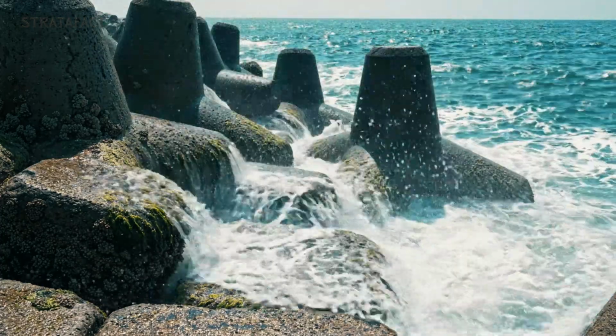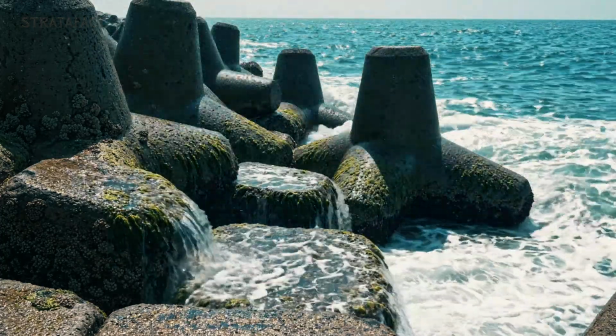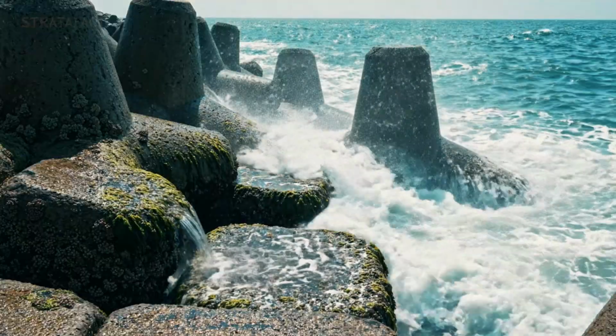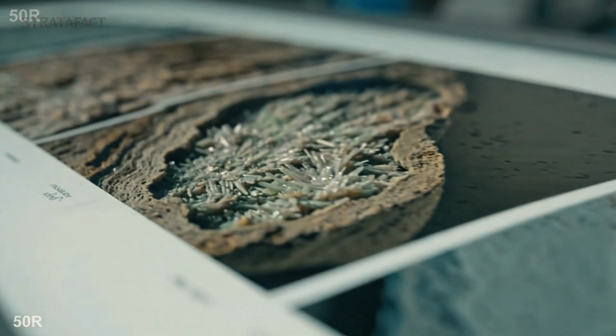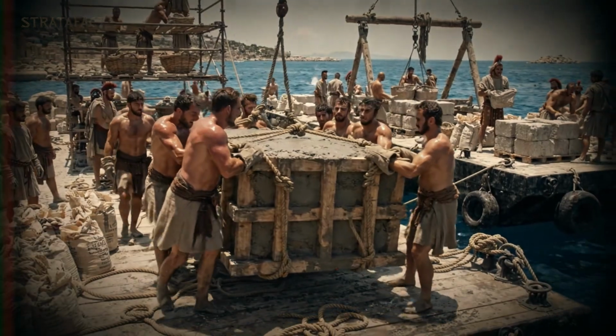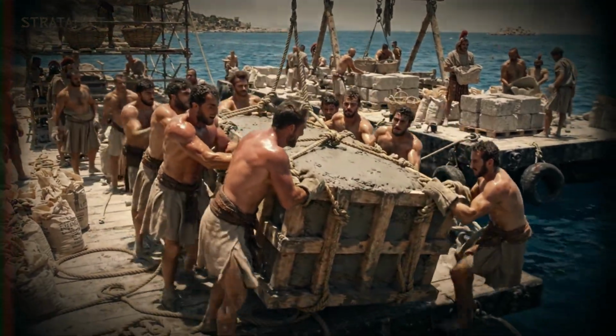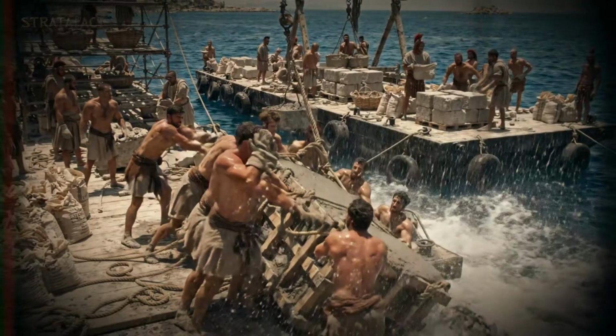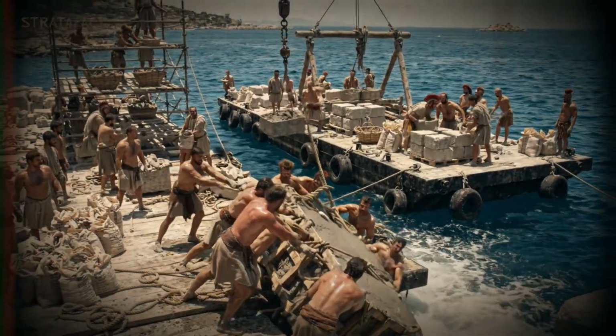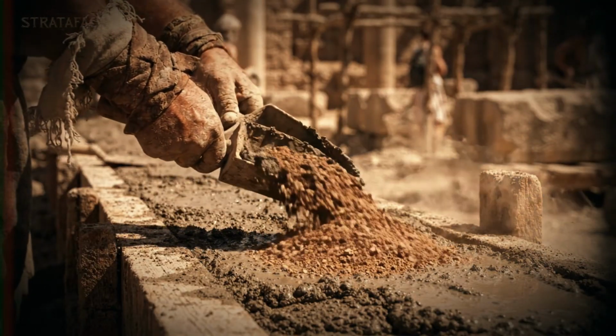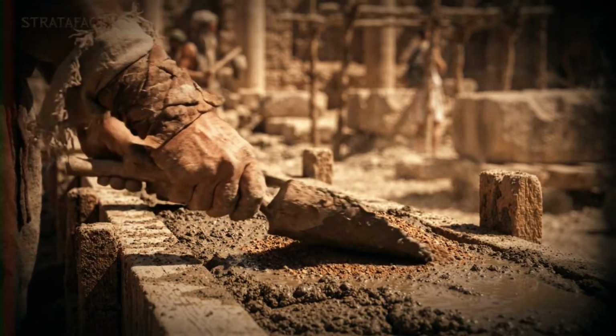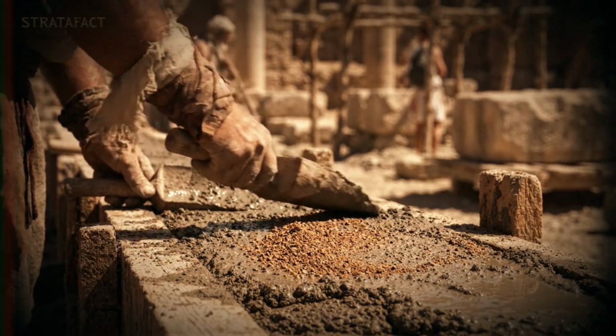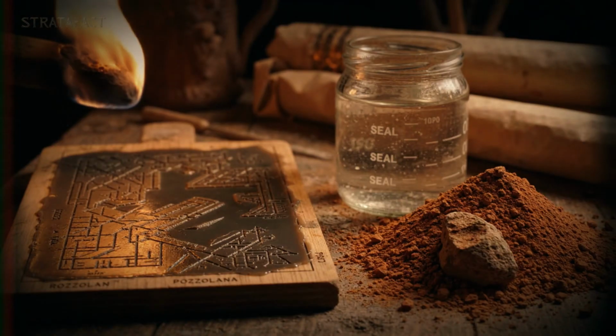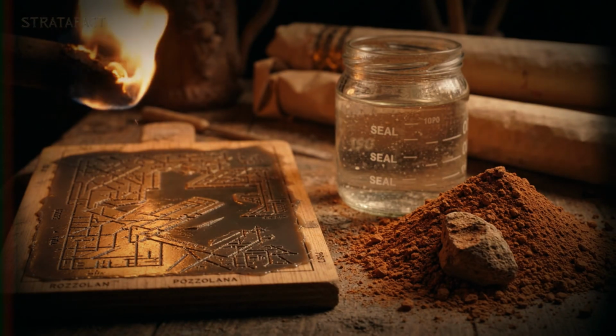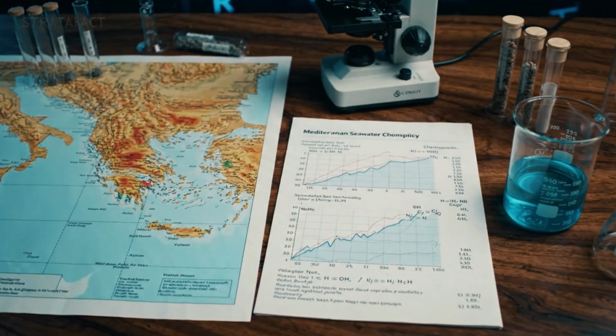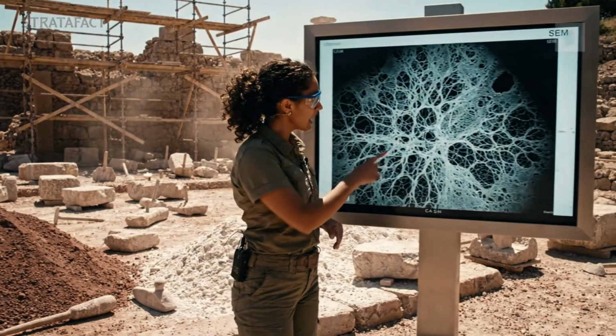The process does not stop. It continues as long as seawater reaches unreacted lime. This is not a property that was designed in. The Romans did not know that their concrete would respond to seawater by growing crystals in its cracks. What they knew was that pozzolana mixed with lime produced a concrete that worked in marine environments. The mechanism that made it work was operating without their knowledge or intention, driven by the specific mineralogy of the volcanic ash they were using and the chemistry of Mediterranean seawater.